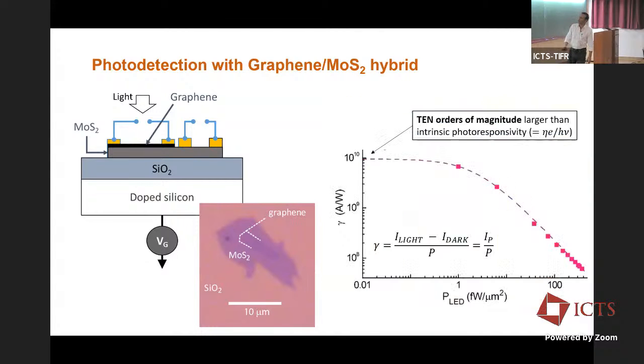And if I look at the number, essentially ampere is the change in current, watt is the amount of power that you shine, and this number gamma is called a responsivity, and that went to 10 to the power of 10 ampere per watt, which for a simple silicon or what we have in the laptops is about 1. So we obtained with this new hybrid structure about a 10 orders of magnitude increase in the optical responsivity of a hybrid structure like this.